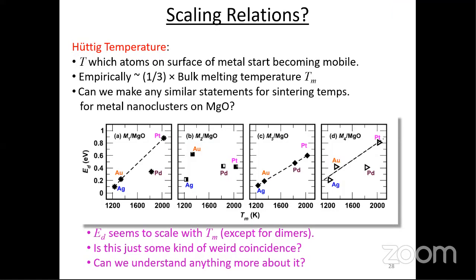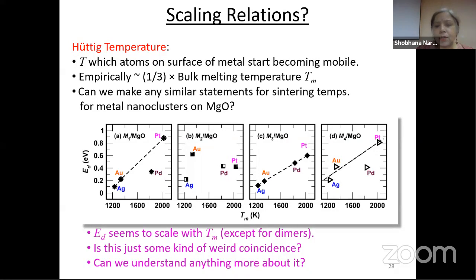Okay, so we're plotting these diffusion barriers versus the melting temperature. And it looks like you have a pretty good scaling for the monomers, the trimers, and the tetramers, but you don't get such a scaling for the dimers. Now, when we first showed these results, everyone said, no, this is really weird. Why should the diffusion barrier of a small metal atom or a small metal cluster on MgO be related to the melting temperature in the bulk? And we had howls of outrage from the referees as well. But I'm going to try to convince you that, in fact, this is a meaningful correlation. And I can also explain to you why we don't have this correlation for the dimer.